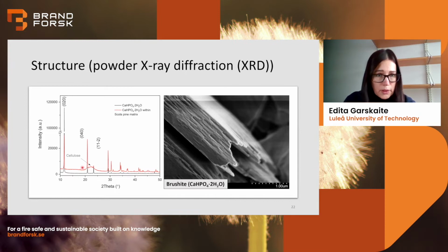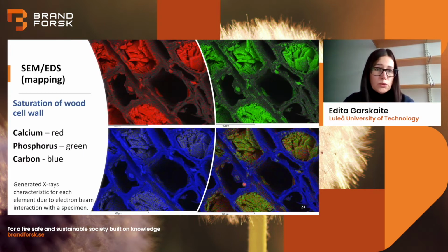So this bump in background is due to the cellulose, and these reflections were assigned to the brushite phase. So this peak shows us that we have a layered structure of material. And it's exactly what we obtained in scanning electron microscopy when we observed the structure of these crystals. So when we determined that we have brushite, then we wanted to see saturation of wood